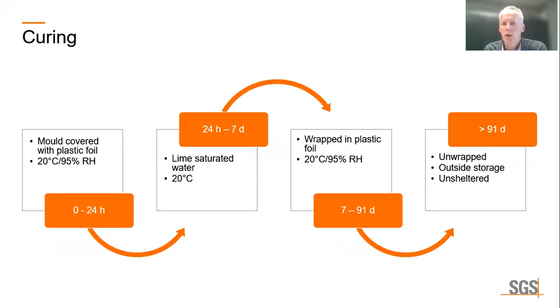Now let's take a look at the curing. The curing up to 91 days consisted of 3 steps, which had to assure that the fly ash concrete mixes show sufficient hardening under moist conditions.